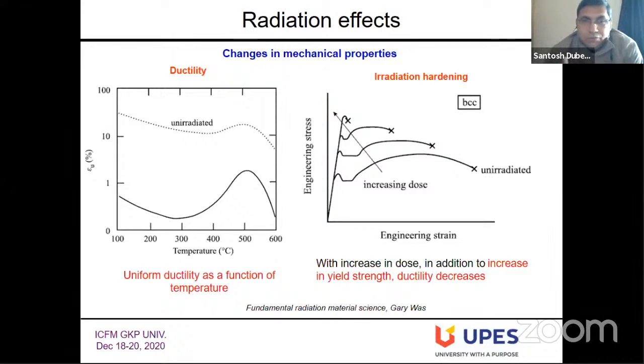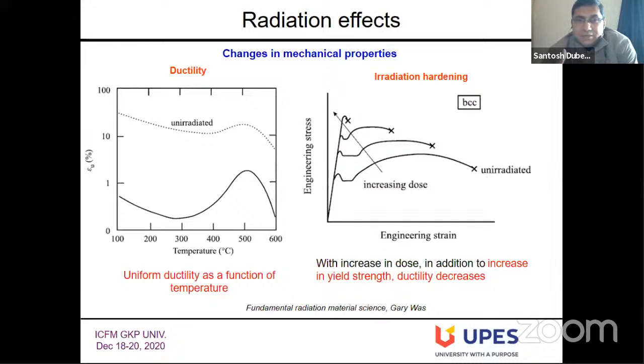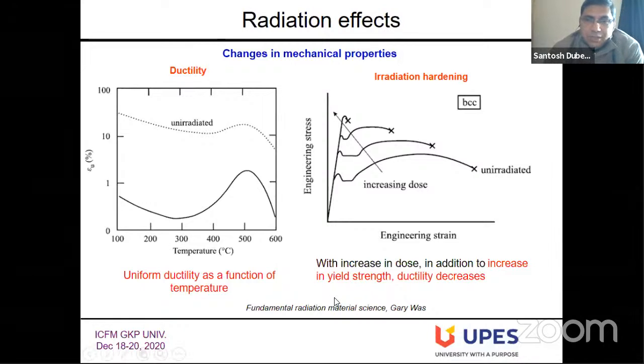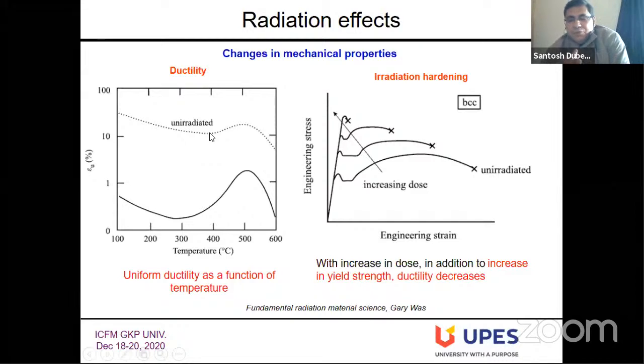The material used before irradiation was highly ductile, it had good ductility property. But after irradiation, the material loses ductility and also has irradiation hardening issues. You begin with a material with really nice, good deformation region, but as you use that material under irradiation, hardening increases. The material has good elastic properties initially, but as time progresses, the material becomes hard.